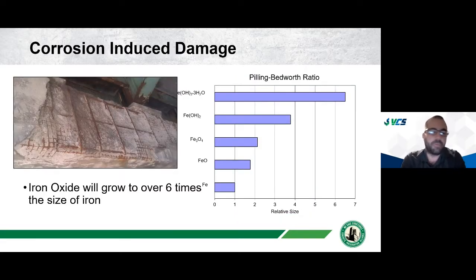So, what do we get when we have corrosion? When we're talking about reinforced concrete, the damage is the result of when the iron becomes iron oxide, it grows in size. And depending on the formation of iron oxide, the size of it can grow up to over 6 times its original size. So if you think about a piece of rebar as it corrodes, it starts to grow inside that concrete, that creates a lot of stress in the concrete, a lot of tensile stress, which will then result in cracking and delamination. So the physical damage of the concrete is due to the expansive nature of iron oxide.